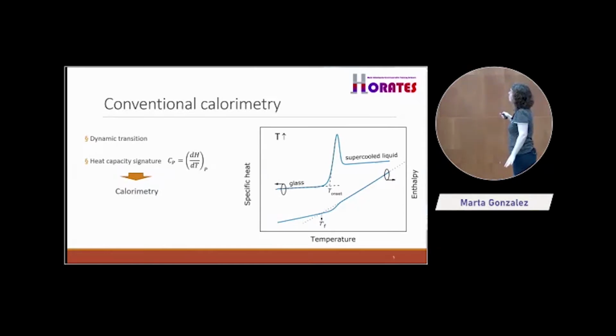Does someone know why we have a jump here in the specific heat curves when we have the glass transition from glass to liquid? No? Some of the experts, the ones that know more about the topic? No? This is because of entropy. This jump here is due to entropy because with this jump we are increasing the degrees of freedom of our system. Here it was frozen. So in entropy, we had the disorder, but it was frozen. It couldn't move. The moment that we can move, we increase in entropy and we have this jump in the specific heat, okay? So these kinds of curves provide a lot of information.